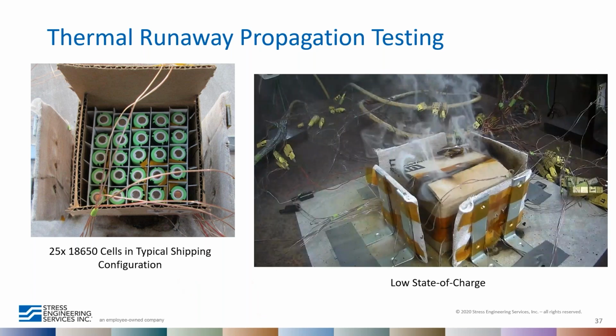Now contrast that with the same test, but with a low state of charge, and all we see is a mild thermal runaway on the initiation cell, some smoke release, but no propagation. So this kind of highlights the requirement that we're seeing for shipping of these cells, where the SOC, the state of charge, has to be less than 30% in order to ship large quantities. Now, what we did see in the testing was that in some cases, even at low SOC, you can still get thermal runaway behavior. So SOC is kind of a stopgap that helps screen cells and ensure a baseline level of safety, but it's not exhaustive.